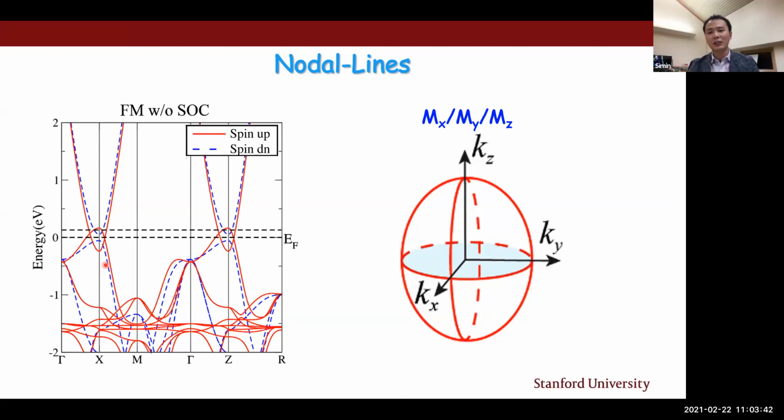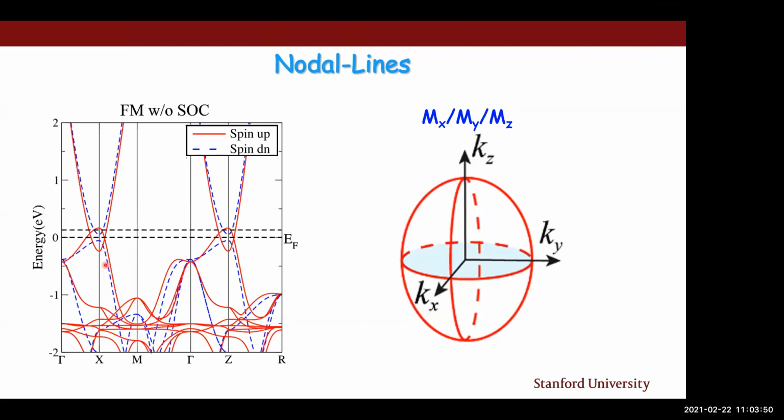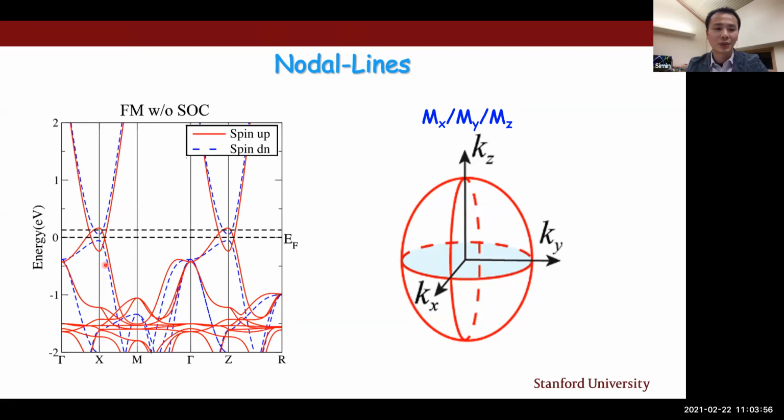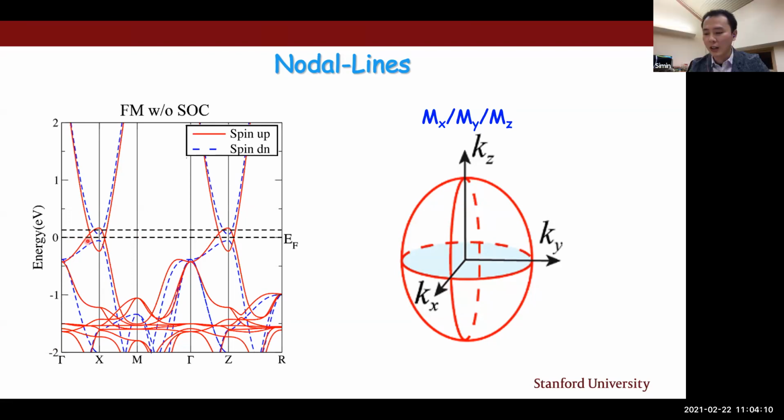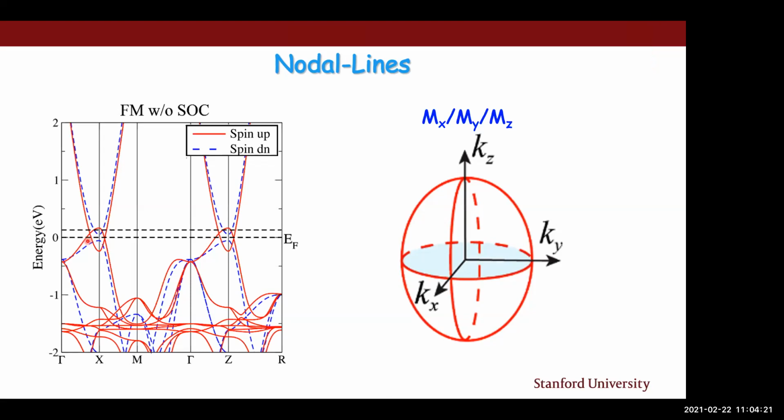I see. Because for the first principle calculations, we assume zero temperature. Are you including some kind of Hubbard U or something? Yeah, we are including Hubbard U. This is why we push the F band away from the Fermi level. If you don't consider the Hubbard U, the F orbital will be around the Fermi level. I see. So the effect of the Hubbard U is just to push the F orbitals far away from the Fermi level, either occupied or unoccupied. I see. Thanks a lot.